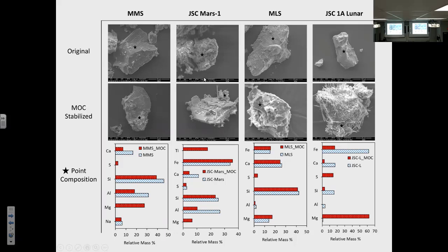Another thing that I noticed was that in the Mars samples, every time we see these platey sheet-like structures, we see more association of the magnesium sulfate with aluminum and silica, whereas in the lunar samples, when we see these needle-like structures, the association is mostly with iron. So definitely we are seeing some evidence of chemical reactions.